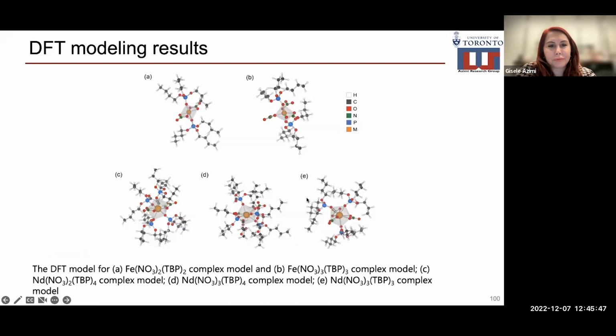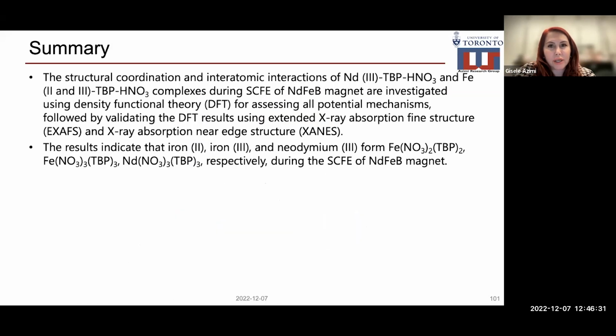in Saskatoon. These are the DFT models for iron and neodymium complexes. For iron 2, DFT predicted iron nitrate 2 TBP2, which is similar to what we proposed. For iron 3, it was iron nitrate 3 TBP3, again similar to what we proposed. For neodymium, 3 structures could be possible: neodymium nitrate 2 TBP4, neodymium nitrate 3 TBP4, and neodymium nitrate 3 TBP3. So we made these complexes after supercritical fluid extraction, and we took them to the Canadian Light Source in Saskatoon to characterize them with X-ray absorption spectroscopy.